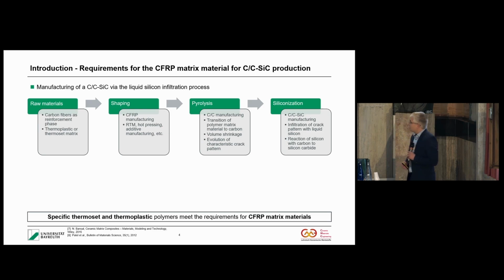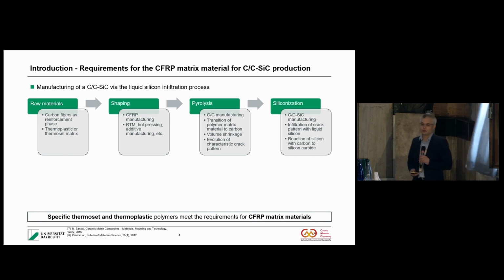So as I was saying, the big advantage for processing CMCs is that you can use developments in the field of polymer matrix composites and then transfer these technologies to ceramic matrix composites. So that means here we have this liquid silicon infiltration process. So you start with the raw materials, with carbon fibers as the reinforcement phase, and then also you have a thermoplastic or thermoset matrix when you process a C/SiC. And here especially you have new developments in the field of polymers, so thermoplastic polymers, and also the shaping technologies of the CFRP. So additive manufacturing, even in the field of PMCs, is developing rapidly.